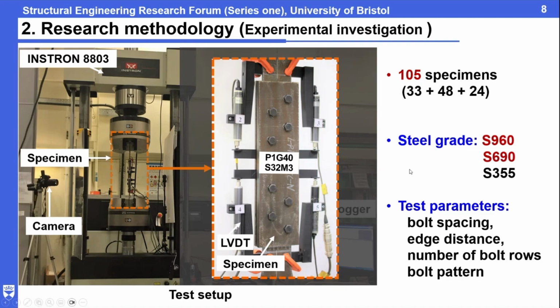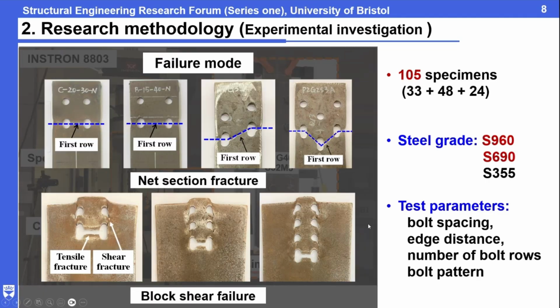And the steel grade covers these two high strengths, and also included mild steel for comparison. The test parameters account for the bolt spacing, both perpendicular to the loading direction and parallel to the loading direction, and also the edge distance, the number of bolt rows, and the bolt pattern, staggered or non-staggered. This shows a typical failure mode from the tested specimens.